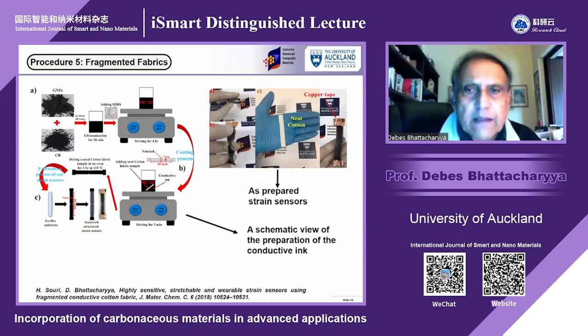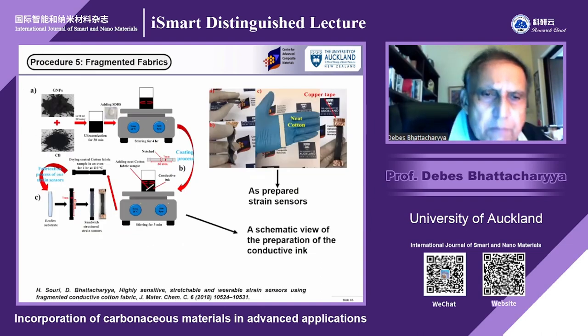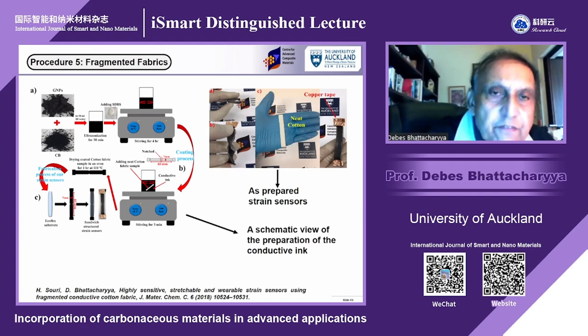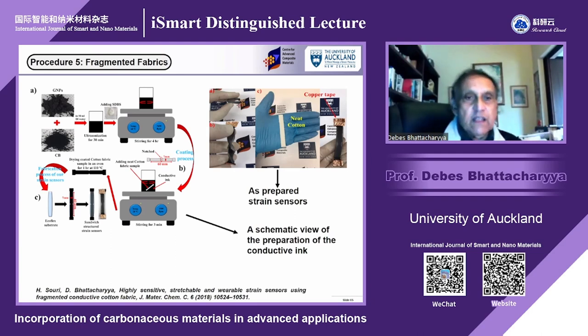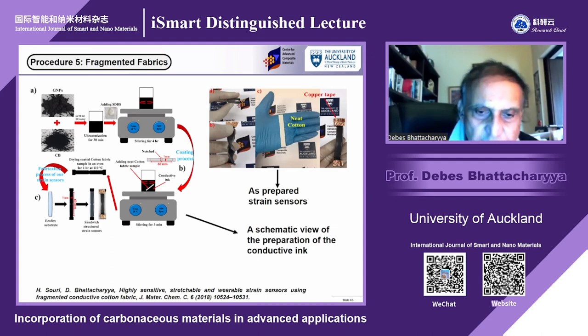So finally, we also use, some people said that if you have a fragmented fabric, you can have a very serious jump because of the change of resistivity. It's quite amazing. I honestly, initially when Amit started working on that, I was not so enthusiastic. But you see that when we found, I'll show you some results. We published all the results in Journal of Materials Chemistry C, and it was fantastic.